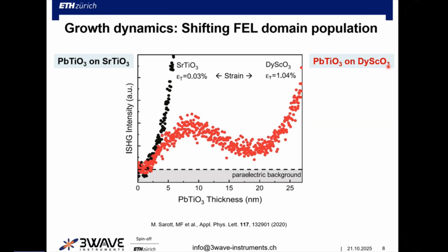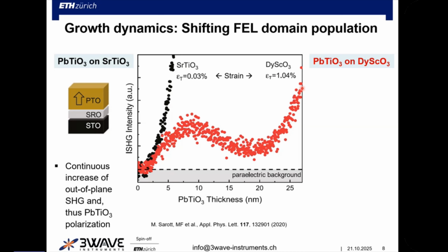But when you grow it on dysprosium scandate, which is exerting strain on the lead titanate, then you see it also starts with an increase of the signal, then a decrease, and then an increase again. So something happens during the growth. And if you analyze this in terms of the polarization of the second harmonic signal, then you find what happens is this one grows as an out-of-plane polarized film all the time.